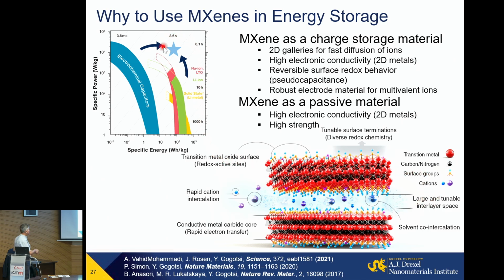But there is one more thing that people rarely talk about. Conductivity. Titanium carbide Ti3C2 has about 2 to 3 orders of magnitude higher conductivity compared to porous activated carbon used in electrochemical capacitors, the fastest energy storage devices. What happens if you have a poorly conducting material and run a high current through it? Because fast charging means one simple thing. You simply run a very high current through a battery or capacitor or any other device.